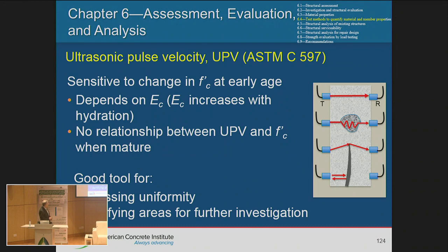We have the ultrasonic pulse velocity. Again, here you have the transducer and the receiver. So you have to have access on both sides of your member, where on one side you put the transducer and on the other side the receiver. You apply a pulse from here and receive it on the other side. The quickest distance between two points is usually a straight line, right? So if there's nothing, it will be a straight line. If you have, let's say, a void, then the time from transducer to receiver is a little bit longer. Or if you have a crack.